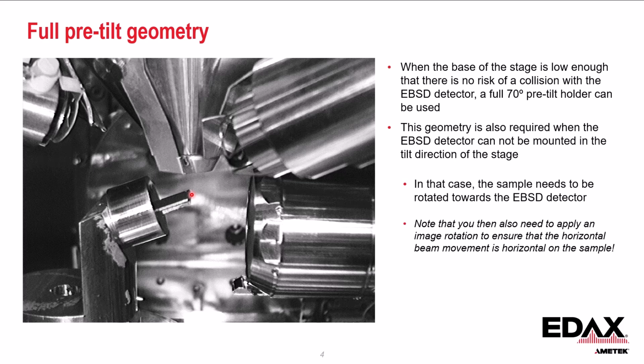But it also gives us a little bit more flexibility for those chamber configurations where the EBSD detector cannot be mounted along the stage tilt axis direction. So when this EBSD detector is mounted at a different angle at the chamber, you have to use a 70-degree pre-tilted holder, rotate your sample towards the EBSD detector, and then you can do your measurements. But you have to be careful. You have to apply an image rotation to ensure that the horizontal beam movement is also horizontal on the sample. So when you are not in the stage tilt axis and you rotate away a little bit, you have to apply a matching image rotation.